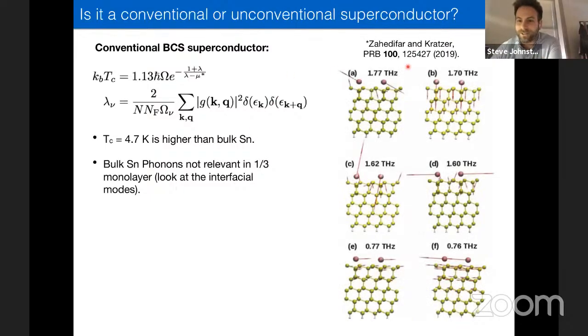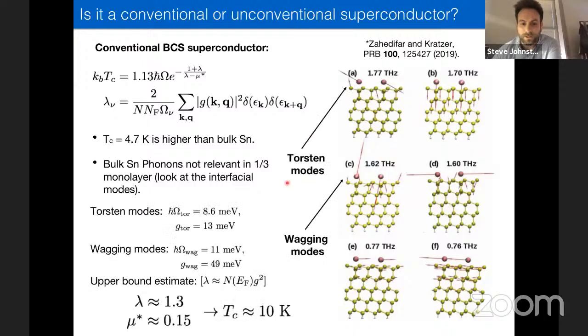So this nice PRB went precisely for this system, for 1/3 of a monolayer of tin on the silicon 111 surface. They actually did the frozen phonon calculations and figured out what the vibrational modes of the tin are on this surface. So these are the dominant modes that they found. And most importantly for us, they found that this torsion mode that I'm showing here, with the tin atoms moving in these shearing motions, and what they call a wagging mode, where the tin atoms move more perpendicular to the surface, are the ones with the largest electron-phonon coupling according to DFT. They get a matrix element of about 50 meV or about 13 meV for these modes, and they're both at about 10 meV in energy.